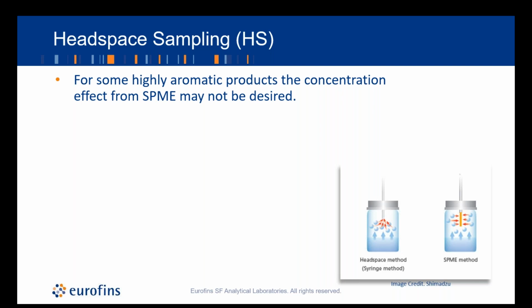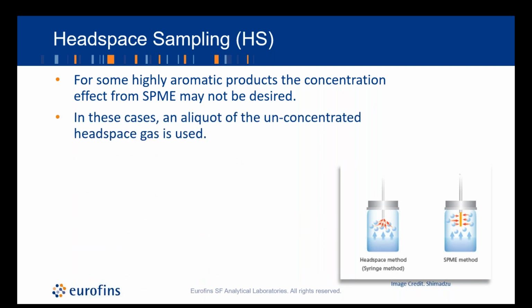So in these cases, we can employ headspace sampling. It works similarly to SPME in that you weigh your sample into a headspace vial and then equilibrate that sample at a given temperature to force compounds into the headspace gas. And then, instead of exposing it to a fiber, you take an aliquot of that unconcentrated headspace gas and inject it directly into the GC. This is useful, like I said, for highly aromatic products, but can also be used to analyze sample off-gassing when you're less interested in the whole volatile profile, but rather what's just naturally released into the headspace gas.